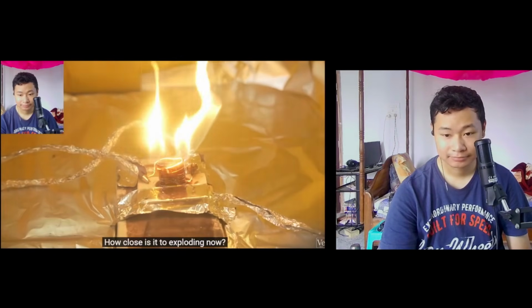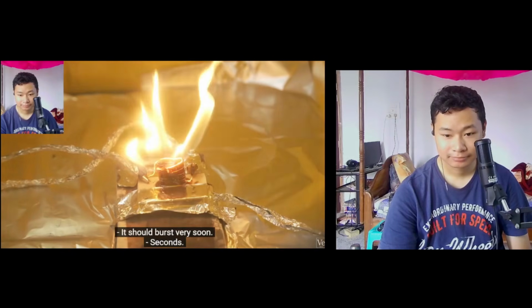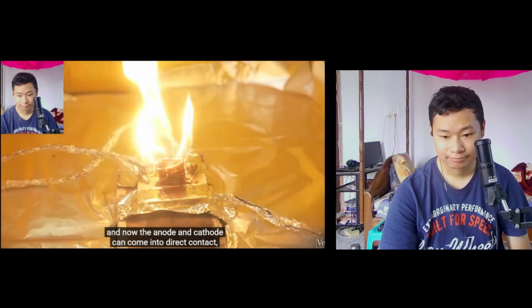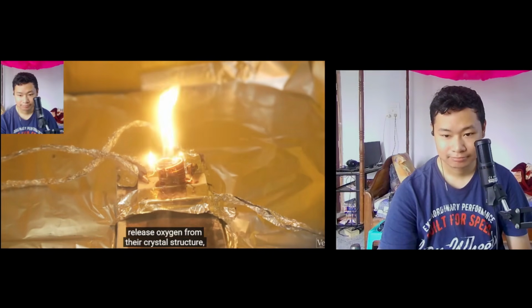How close is it to exploding now, what do you think? It should burst very soon. At roughly 130 degrees Celsius, the polymer separator is going to melt. And now the anode and cathode can come into direct contact, and a massive internal short follows. The cathode itself starts to decompose, and because transition metal oxides release oxygen from their crystal structure, they're going to fuel the combustion. And now the fire is just feeding itself.